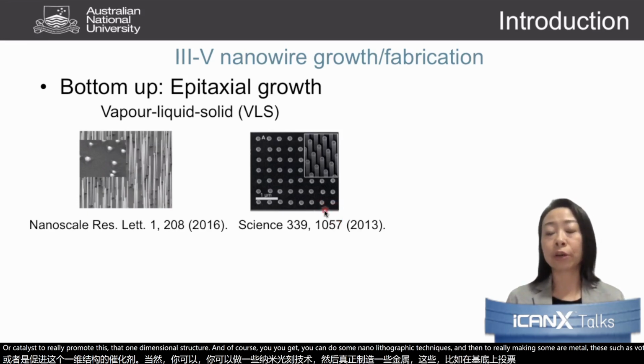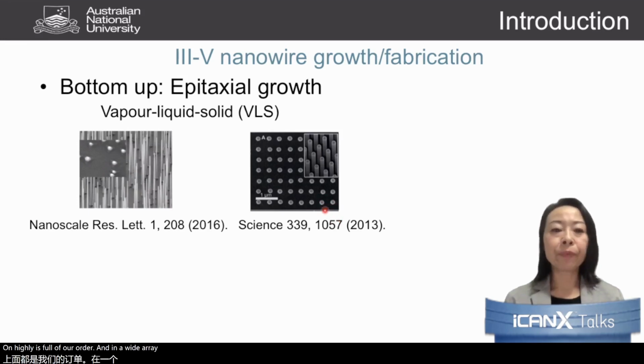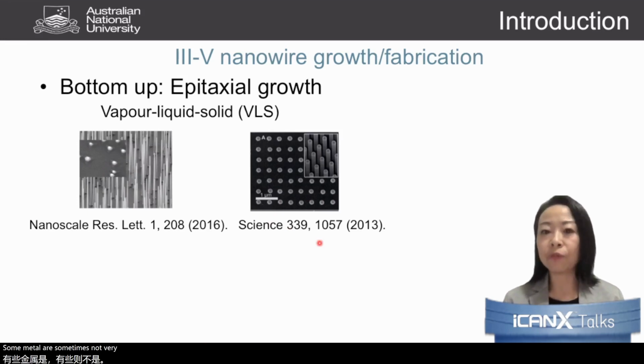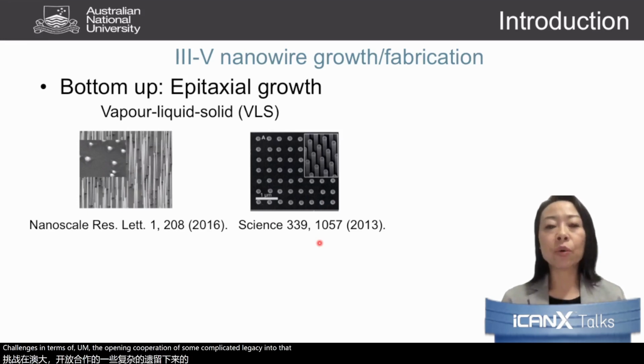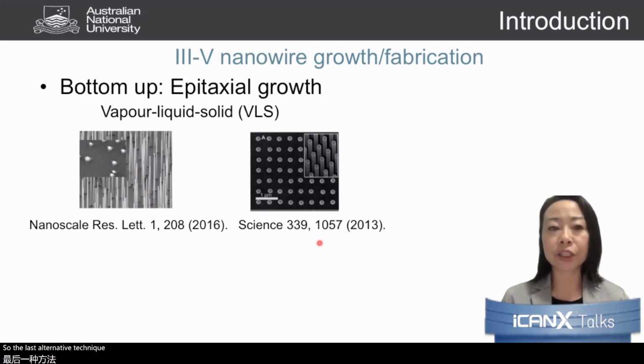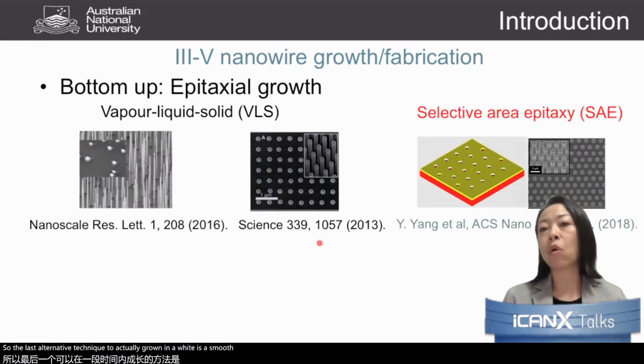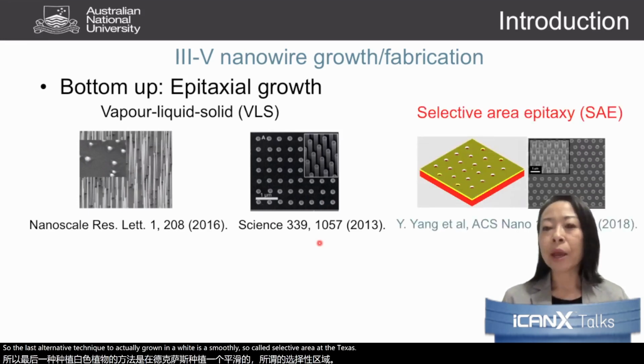Thereby, you can actually grow also very highly ordered nanowire arrays. However, this technique, of course, involves some metal. Sometimes it's not very desirable for device applications. And then there are also some other challenges in terms of dopant incorporation, some complexity in that. So another alternative technique to grow nanowires is the so-called selective area epitaxy, which is the technique I'm